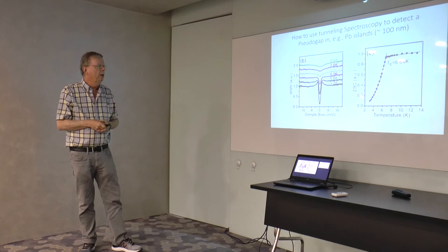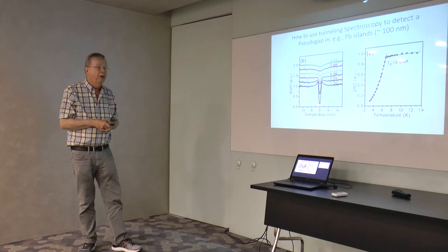So if I look way below, or somewhat below T_c, I get, as you see, a big dip in the middle, not flat, getting worried here. Coherence peaks, that's good. So we sort of see behavior that you might associate below T_c with scanning tunneling microscopy. And as I get warmer, even though I'm below T_c here at 6 Kelvin, I see no coherence peaks. So the two things you're looking for, one of them's missing. But people that do STM say, hey, here is a dip in the density of states. This is the conductance. Here's a dip in the density of states around zero. This is like an opening of a gap.